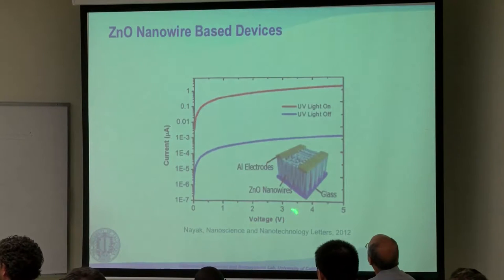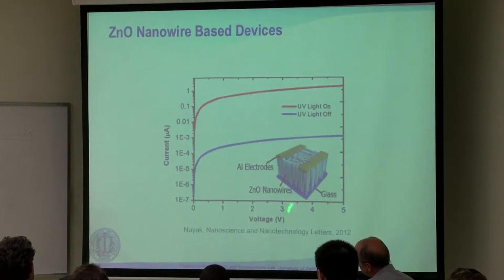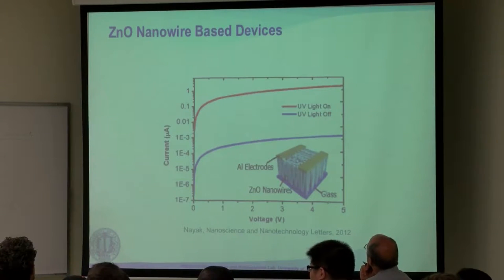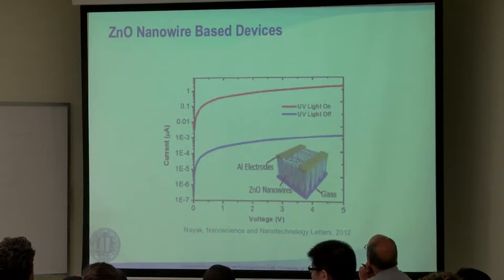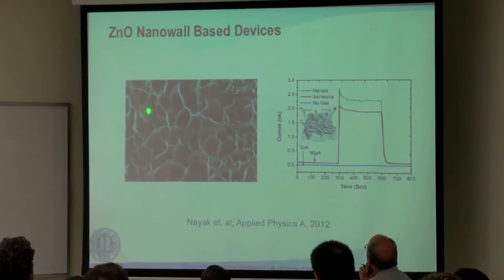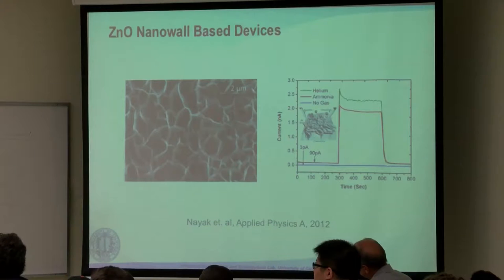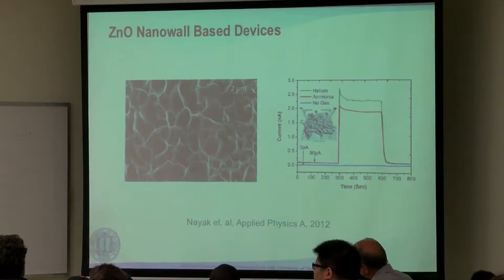We demonstrated some sensors. Here you're looking at zinc oxide nanowires grown on glass substrate. This is meaningful because suddenly your window can be intelligent, or your T-shirt can be intelligent, because you're now capable of integrating this kind of material. You can grow them at extremely low temperature without destroying those materials. These other nanostructures look like nanowalls — they are really good as sensors because they're full of surface, and when something has so much surface, you can easily detect extremely low concentrations of harmful gas.